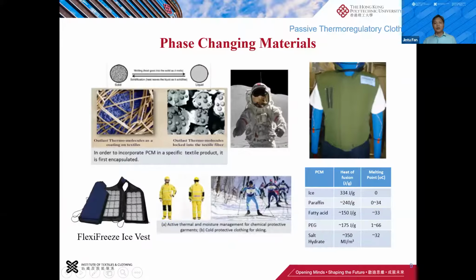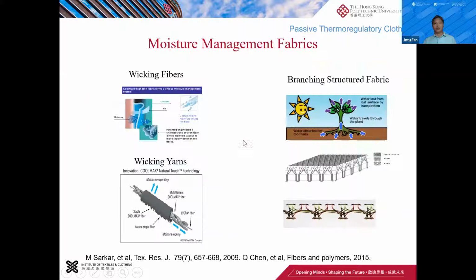Now, those are the natural fiber materials or conventional fiber materials. Another very common thermoregulatory material for clothing is what we call phase-changing materials. Phase-changing material could contain water or ice or paraffins or fatty acids. It was originally invented by NASA, but is being used in clothing. But generally, to have a relatively long-term effect, it has to be very heavy. Like this jacket, it's very bulky and heavy. It probably can only work for half an hour in terms of its effect.